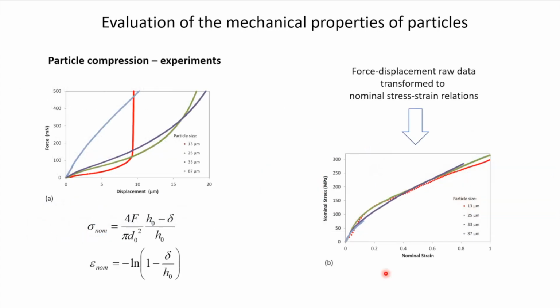So if you look at the raw data of force displacement here, you see that for different particle sizes, you see quite a different kind of result. But it could be misleading, because what you really need to look at here is not the raw data, but some representative or characteristic stress versus strain. So by doing some simple mathematical transformation, you can plot some nominal stress value versus nominal strain, and you see that all the particles are also following almost the same trend.